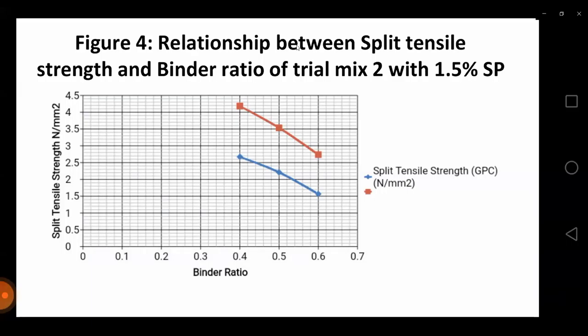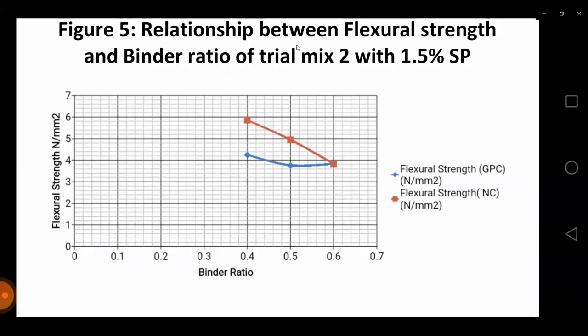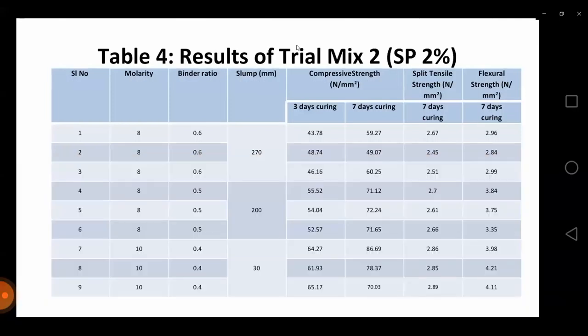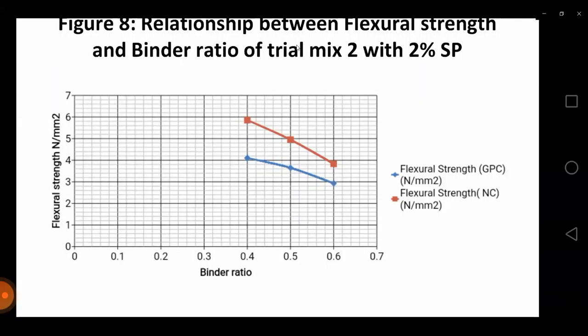And this is the relation between the flexure strength and the binder ratio. Again, here also the normal concrete gives more flexure strength than the alkali-activated slag concrete. So these are the results of the same trial mix 2 when we use the superplasticizer at 2%. And this figure shows the flexure strength and the binder ratio of trial mix 2 with 2% of the superplasticizer. So here also the normal concrete gives more flexure strength than the GPC.